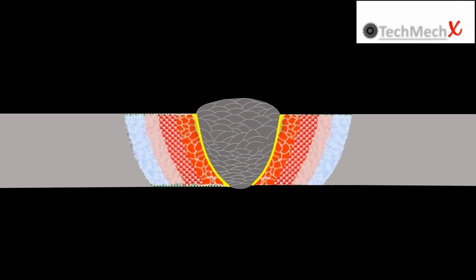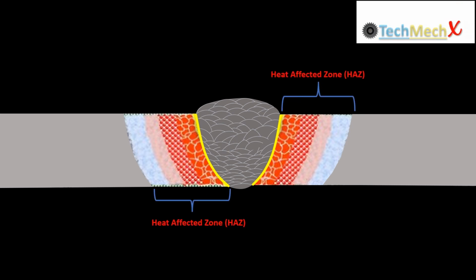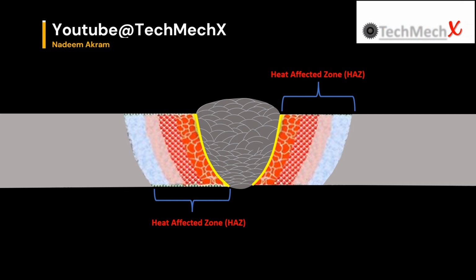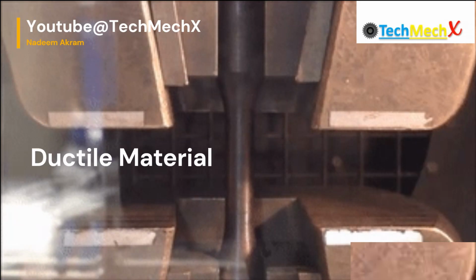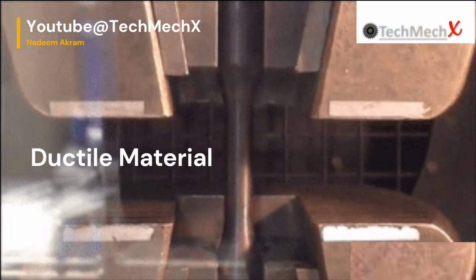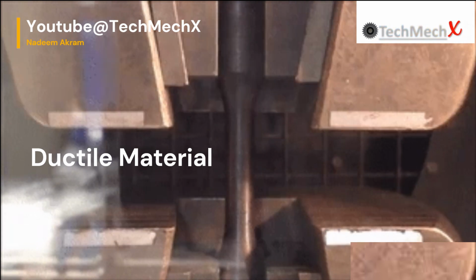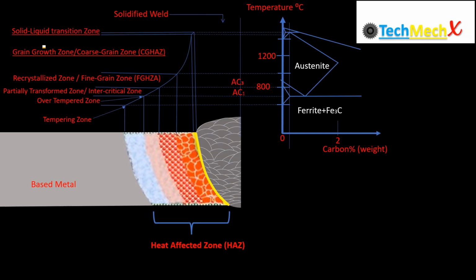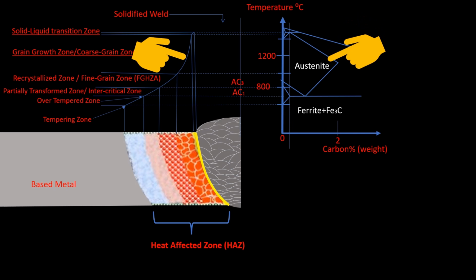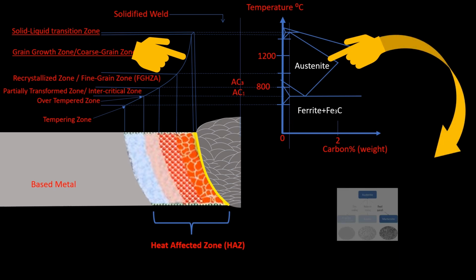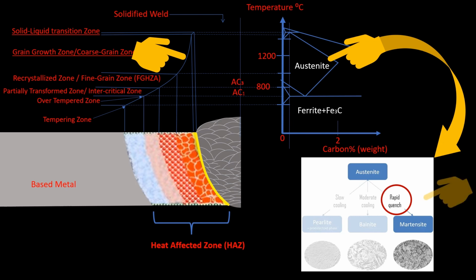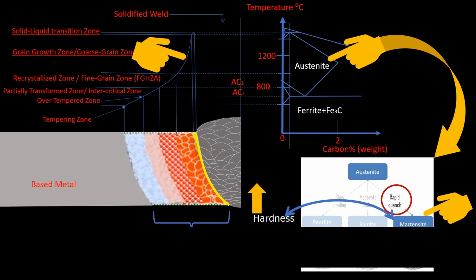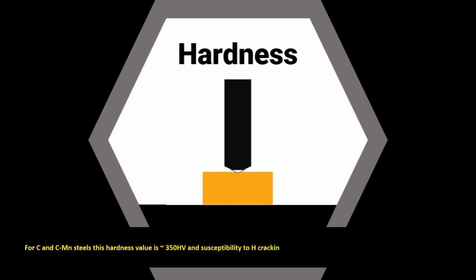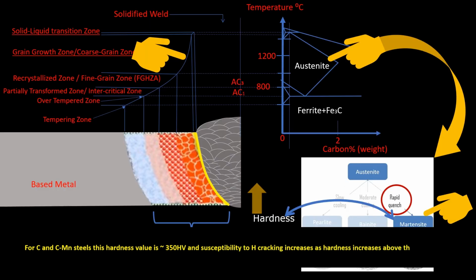The heat affected zone can become brittle due to the hydrogen, making it susceptible to cracking under localized high stresses instead of undergoing plastic deformation, stretching-like behavior. A susceptible microstructure is one that contains a relatively high proportion of hard, brittle phases of steel, particularly martensite. The heat affected zone hardness is a good indicator of susceptibility when it exceeds a certain value. For carbon and carbon manganese steel, this hardness value is 350 HV, and susceptibility to hydrogen cracking increases as hardness increases above this value.